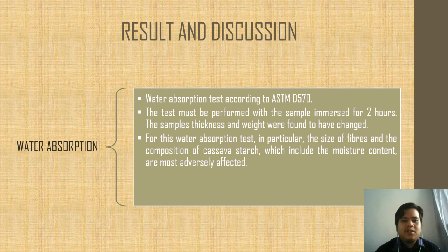Next is the water absorption test. The water absorption test is according to ASTM D570. The test must be performed with the sample immersed for 2 hours in water. The sample thickness and weight were found to have changed. For this water absorption test in particular, the size of the fiber and the composition of cassava starch, which includes the moisture content, are mostly affected.